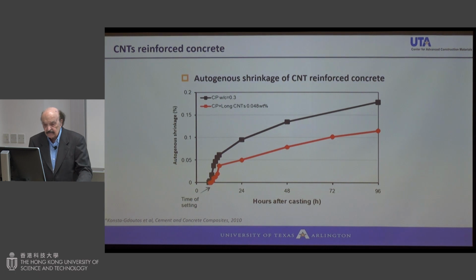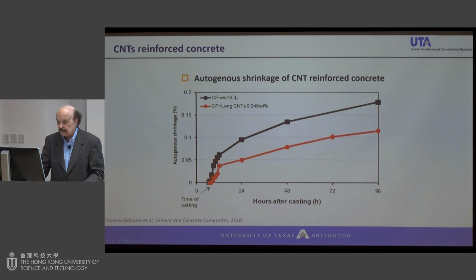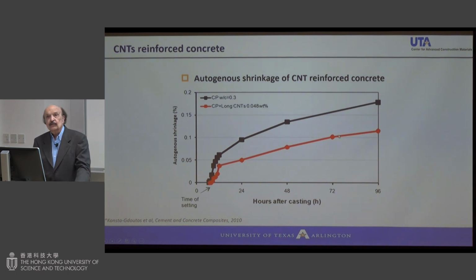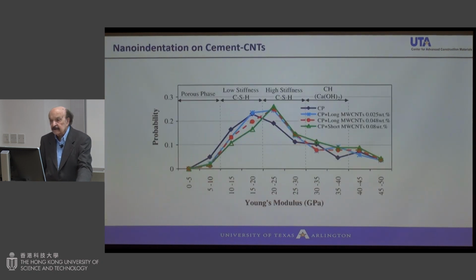Also very interesting, for so-called high performance concrete with a low water to cement ratio, you have an issue of autogenous shrinkage. And addition of CNT, this very small amount, 0.048%, reduces it. So with all the other advantages of CNT, we are now asking whether CNT can increase CO2 uptake substantially, and we are also adding high calcium fly ash to really add more waste material. Many of you are familiar with what happens with CNT at the interface: you find more so-called high density CSH when you have this graphene-based material.